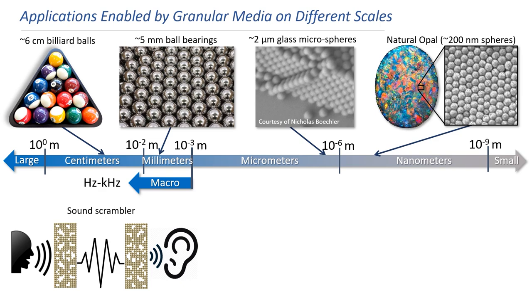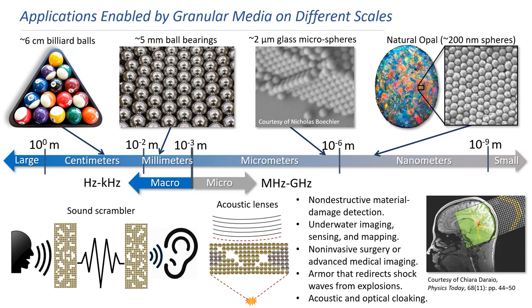The really neat applications, though, are achieved using microgranular crystals that consist of micron to nano-sized spheres. Unlike macro-sized granular media, microgranular crystals behave like an actual material in that intermolecular forces passively hold their spheres together without them needing an external container. More interesting, however, is that the small spheres that constitute microgranular crystals enable them to support mega to gigahertz frequencies for high-energy applications. Examples include acoustic lenses that focus high-energy stress waves to a desired focal point, which can be focused tighter and tighter as the crystal spheres are made smaller and smaller.